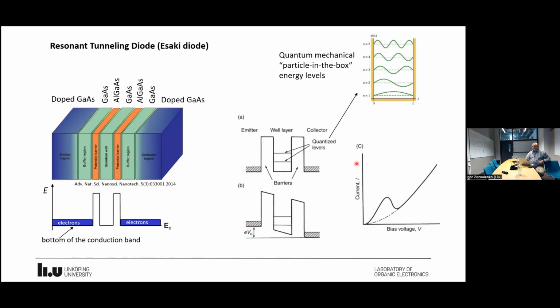And when you look at the current-voltage characteristics of this diode, you will see an increase of the current. But then when you apply further voltage, this level will go down and the condition of resonant tunneling disappears, and then the current decreases. So basically here you will have a typical diode behavior with a negative differential resistance, and this behavior is based essentially on the quantum mechanical resonant tunneling effect.